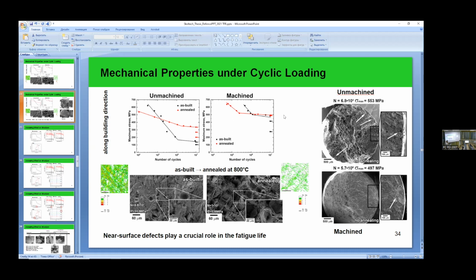So here you have put arrows, right? I asked you questions on that in your comments as well. You have 3 data points showing the runout condition for the annealed sample in the unmachined condition. See, 3 red data points, right? So what does that mean? You have tested 2 more samples to verify, and it appears that the annealed sample is going very close to the as-built one, in the endurance in one of these cases.